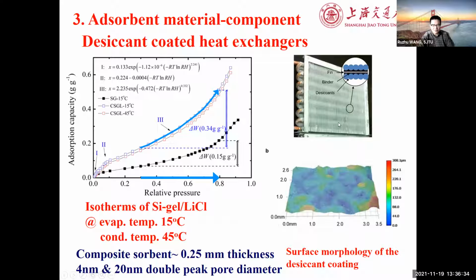Why do we do this? To compare the silica gel with this composite, it's very linear. And if we have relative humidity changes from 30% to 80%, then what you could see is that the W value could be increased just 100% or even more. The sorbent is only about 0.25 millimeter thickness.